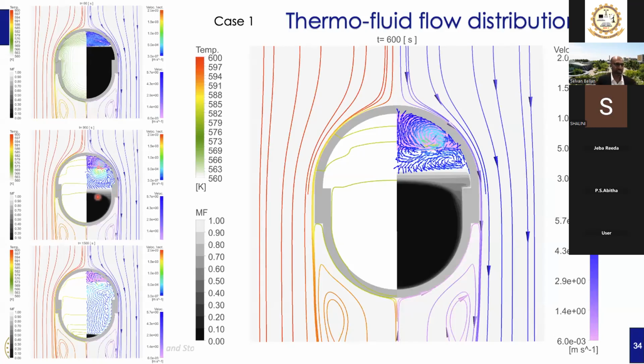As you can see, initially there was airspace for thermal expansion, and as it melts, it shrinks. So the airspace is gradually decreasing, you can notice. Moreover, during the melting process, the solid phase sinks inside and pushes the thin liquid layer formed at the inner surface of the capsule. As a result, it pushes the liquid towards the top part along the inner surface of the capsule. It creates a kind of anti-clockwise natural convection pattern, which increases the heat transfer rate. Like that, we can obtain very detailed heat and mass transfer characteristics inside the capsule.